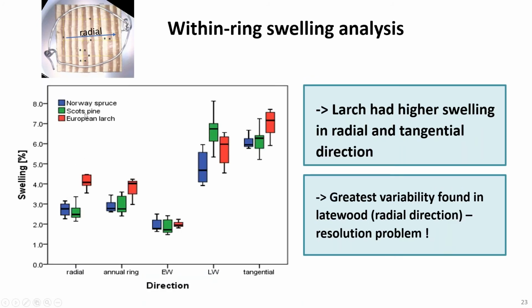resolved in individual species, we realized again that the larch is kind of special. It has the highest swelling in radial and tangential directions. The late wood, because of the variability resolution issue, I'm showing here the greatest variability found in late wood, but because of the resolution, we don't see the larch being highest. That's a resolution issue. So high resolution of the video camera is important. Okay. Within ring swelling analysis.